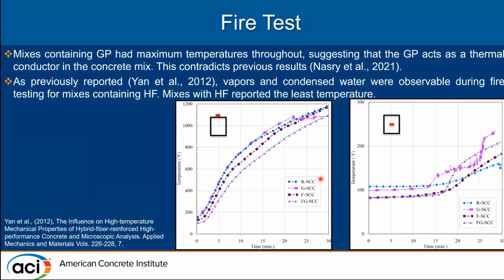So, like I said, the fire test was carried out as per ASTM E119 standard, and the fire exposure time was 30 minutes. And the maximum temperature the specimens were exposed to was 1550 degrees Fahrenheit. So these curves basically highlight the different surface temperatures. To begin with, I have the top surface temperature and the core temperature of the beams. It was observed that the mixes with glass Pozzolan tend to have higher temperature gains when compared to all other mixes, and the mixes with the hybrid fibers generally had very low temperatures.